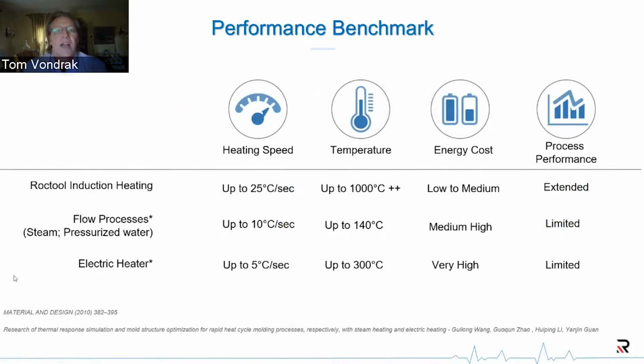All right, let's talk about induction. I would have you concentrate here on some of the benefits of Roctool induction heating versus some of the other ways to heat a tool. On the first line, you see heating speed, up to 25 degrees centigrade per second heating, really unlimited temperature. We can go up, we say here, up to 1,000 degrees centigrade. That's not necessarily for an injection molding application, but we do some applications where we have heated mandrels and we're doing bending of high heat materials where we can get up there. Very efficient from an energy perspective and really gives the widest possible process window for you.